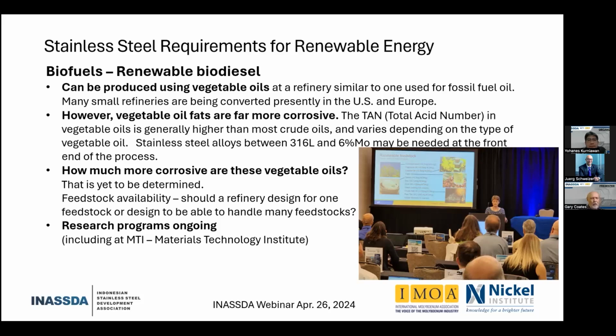So rather than using chrome moly steels or even carbon steels, which you can use in certain fossil fuel refineries, you need to start off at the front end with anywhere between 316 and 6% moly stainless steel, depending on the type of vegetable oil used as a feedstock. And of course, a refinery has to consider: can we always get a particular type of vegetable oil, or must we design our plant to handle different types? So often they're going for the more conservative approach of a higher alloy material at the front end. There are a lot of research programs going on. I'm involved with one at the Materials Technology Institute, where they're sponsoring some research to determine how corrosive these materials are. We'll also learn as these other plants start up.